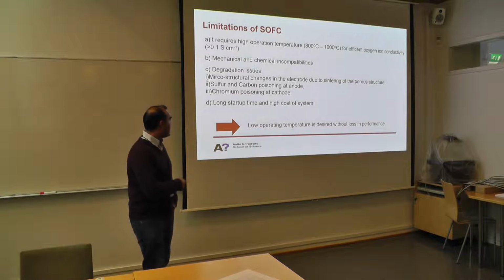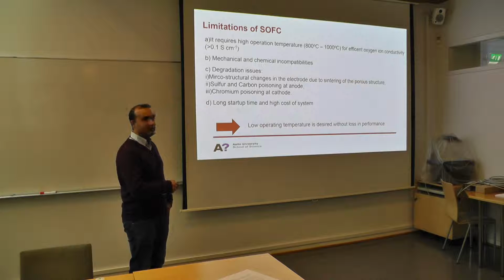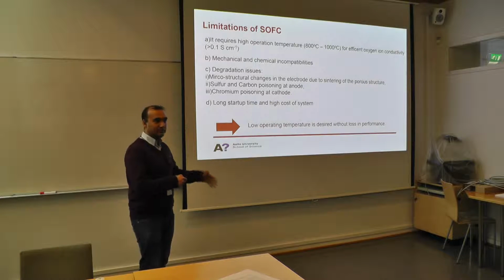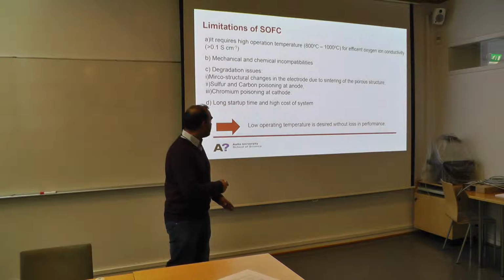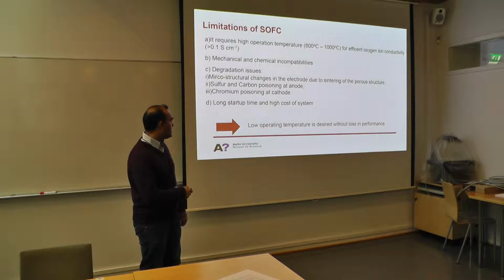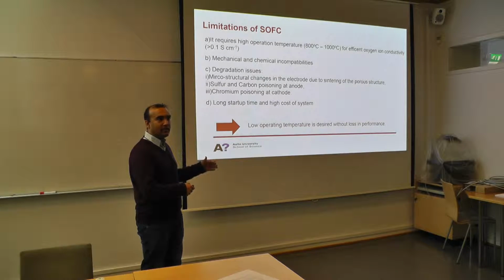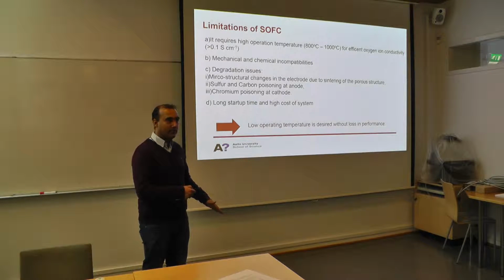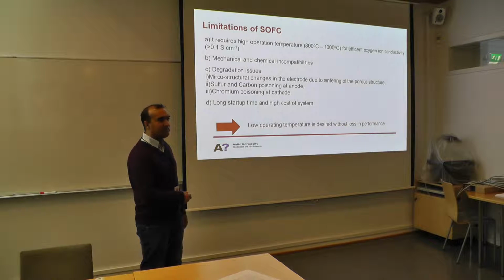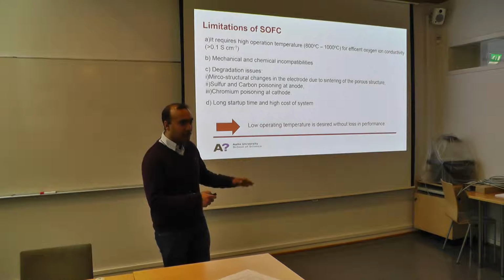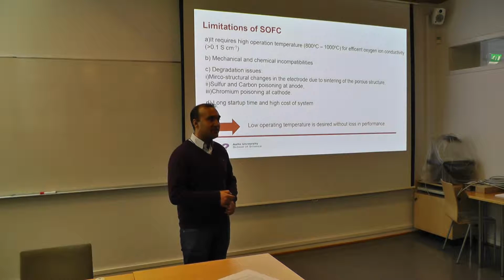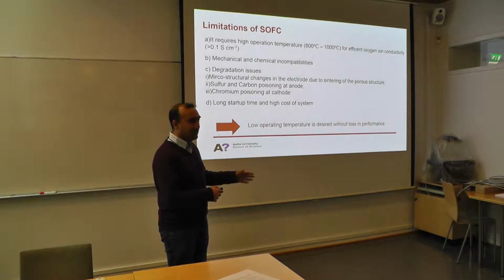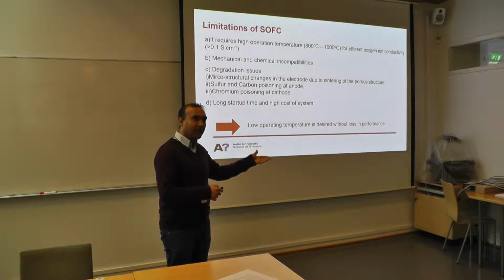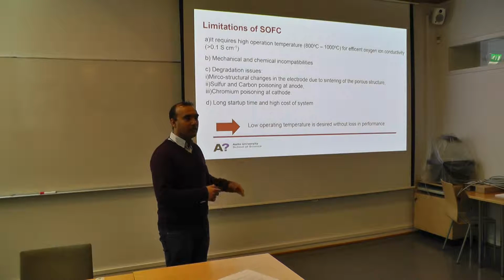And another thing is it has very long startup times, and these systems are very expensive. So these are the problems. The main idea of showing this slide is to show that this high temperature is an issue, and we would like to decrease its operating temperature. That's the main thing. But at the same time, we don't want to lose any performance, because these devices give, let's say, 1 watt per square centimeter at 800 degrees, but we would like to get the same performance at lower temperatures.